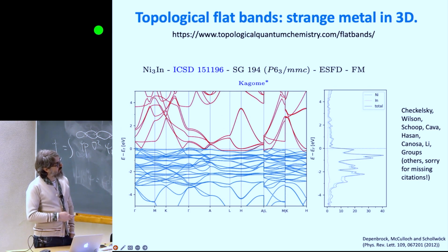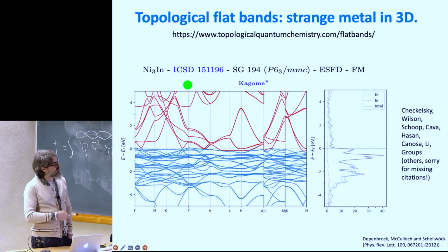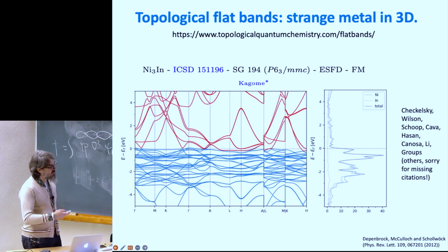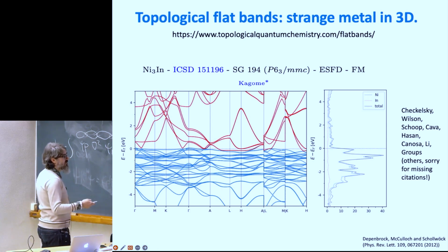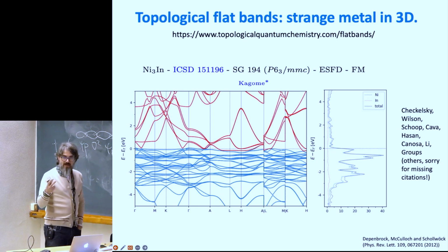For example, this is one of the Kagome materials, and you can see clearly that it's got some very flat bands at the Fermi level. By very flat, meaning 100 milli-electron volts dispersion, etc., which is very little in a material of bandwidth 8 electron volts, or so, from, for example, here to here. This is a huge bandwidth, but there's some very flat bands. These come from the Kagome lattice.